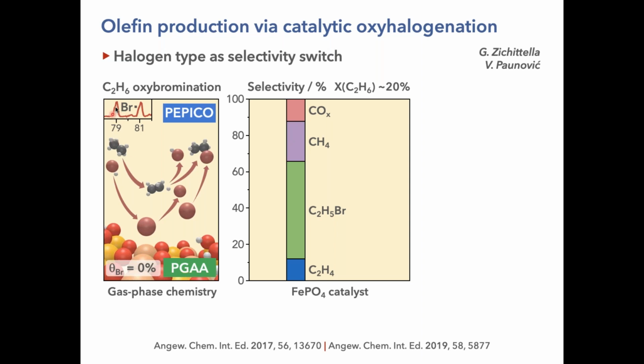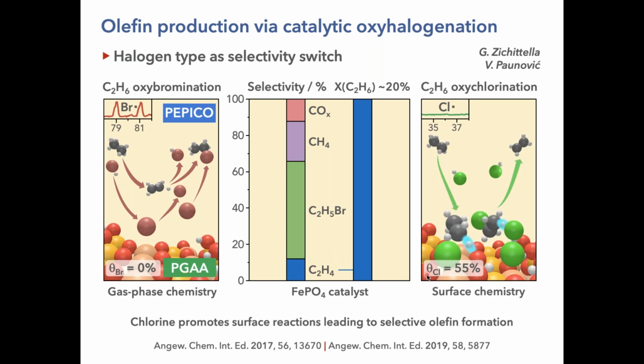And we see that because bromine is always appearing in PEPICO in the gas phase, while the coverage of bromine on this catalyst surface, in this case an iron phosphate catalyst, is close to zero. So what we need to do with ethane is to bring all this chemistry down on the surface. And that you can do by using chlorine, because chlorine will adsorb more strongly on the catalyst surface. And so you can operate the reaction so that there is no radical formation in the gas phase. So this is ethane oxychlorination.